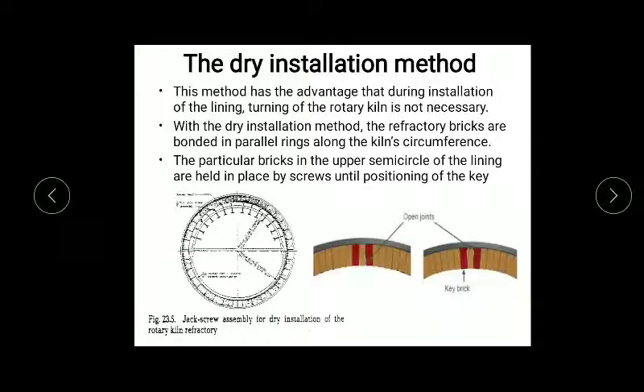In dry installation, you are not using any adhesive or any cementing material in order to paste the refractory to the surface of the shell. You are directly screwing all this refractory to the shell at first. Initially you are using screw jacks to screw them to the surface. Then once they are all lined, only one gap is remaining. You fix that gap with a key brick.